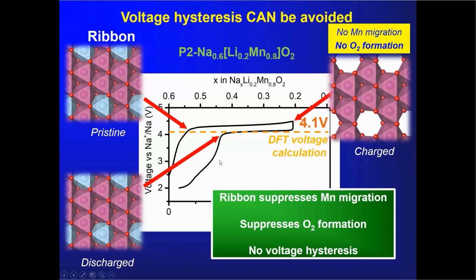Not perfectly, and indeed on cycling you do lose this. So this is not a silver bullet for the industry to have a material, but it, I think, scientifically shows us that it is possible to suppress the molecular oxygen and get true reversible oxygen redox.